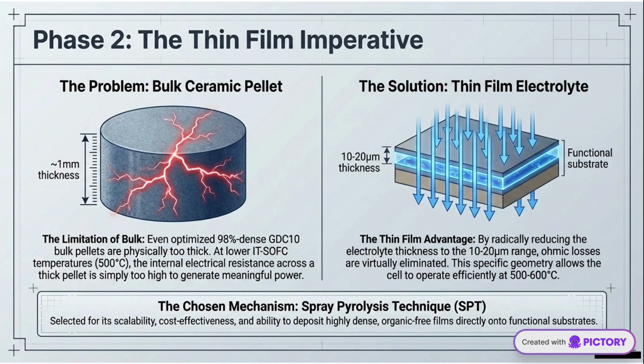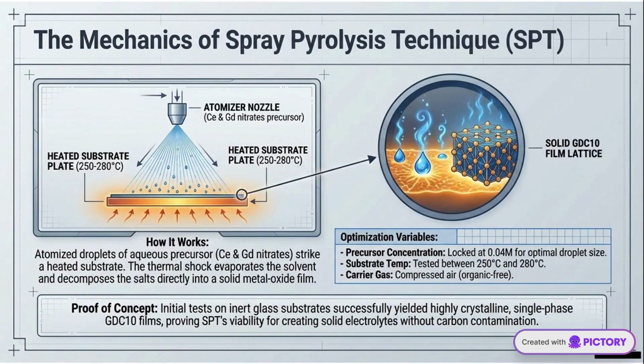Transitioning to thin-film electrolytes addresses the limitations of bulk ceramics. By reducing thickness, we improve functionality and efficiency, paving the way for advanced SOFC designs. The spray pyrolysis technique allows for the creation of high-quality GDC-10 films. By optimizing variables like droplet size and carrier gas, we achieve dense, crystalline structures without carbon contamination.